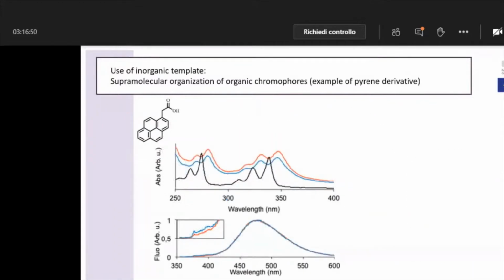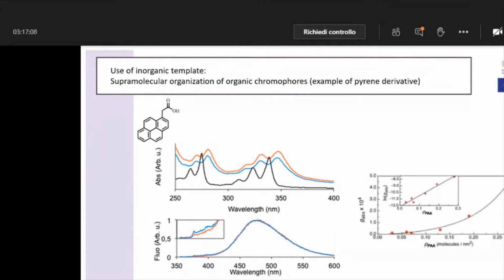If you change the density to a much higher value, so you graft more of the molecule on the surface, then you can increase by a lot the ratio of the excimer to the monomer. And here you have almost only excimeric fluorescence. Looking at the chiroptical property, we find that by increasing the density of the molecule, the g factor, the dissymmetry factor of your material, increased tremendously.